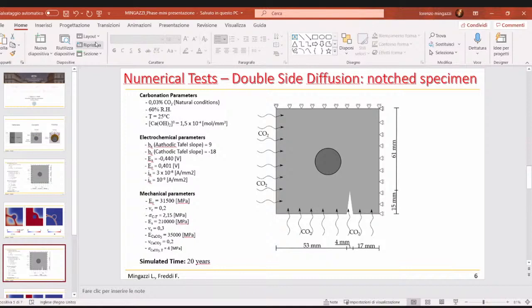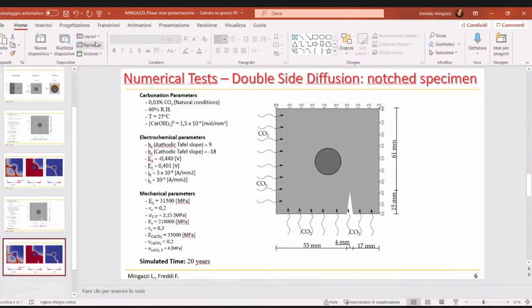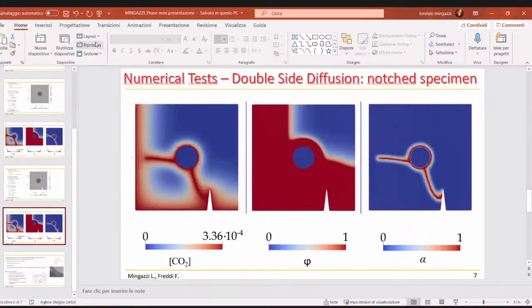However, we introduced a notch on the bottom side of the specimen to see the effect that pre-existing cracks or defects into the concrete cover could have on the simulation and the results of the model proposed. As we can see, the carbonation profile obviously follows the different geometry of the specimen. So it changes accordingly. And moreover, the phase field, the crack pattern, also follows the changes into the environmental condition.